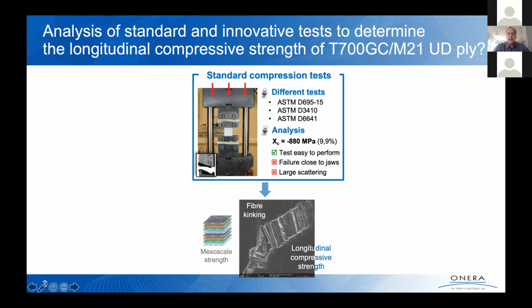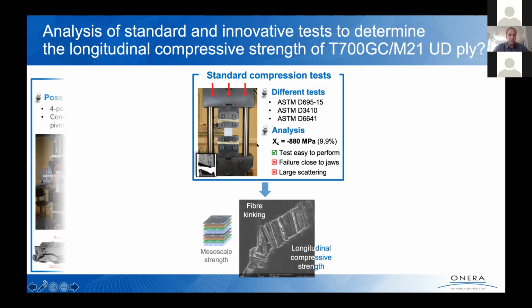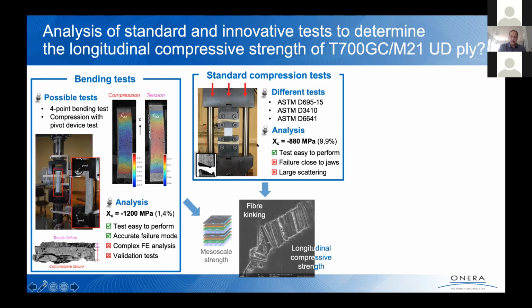So the idea is to propose a test in which we better master the boundary conditions that we are going to apply to the specimen in order to measure the strength. So you can do that considering a bending test, because for lots of carbon epoxy materials, the longitudinal compressive strength is 2 times lower than the longitudinal tensile strength. Therefore, you can perform a 4-point bending test.